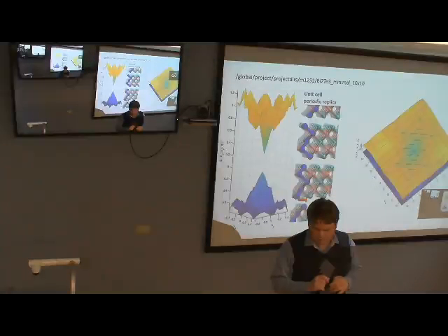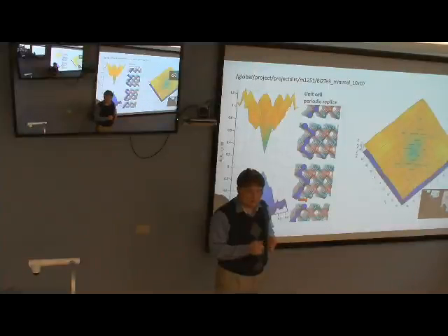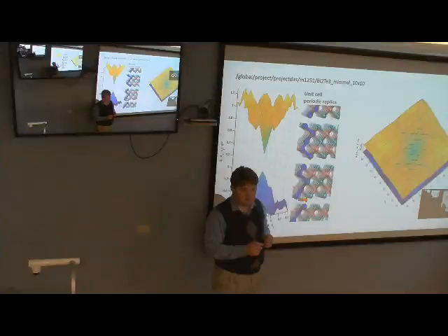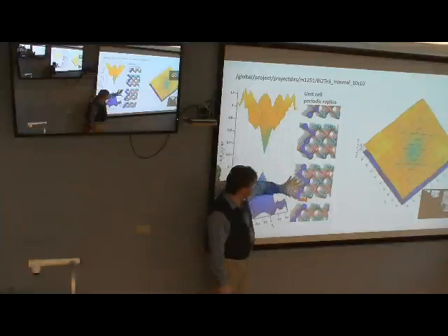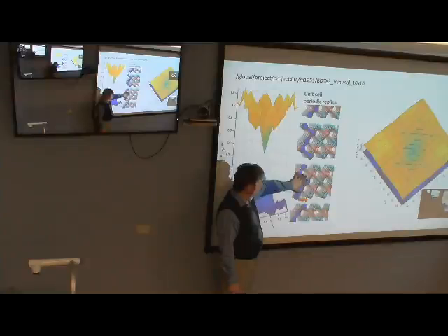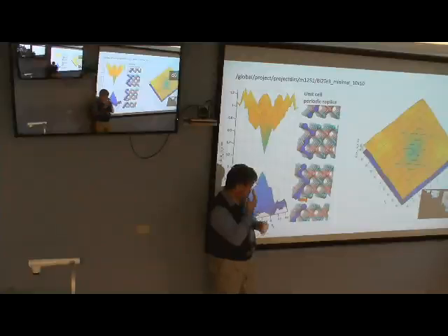So one of these materials is bismuth telluride. Bismuth is trivalent, tellurium is divalent, so the stoichiometry is bismuth 2, telluride 3, and it is similar to Dr. Colbert's question to David yesterday. It is a 3-dimensional material in terms of synthesis, so it's bulk, periodic in all 3 directions. But the internal structure is composed of layers that do not have chemical bonds between them, same as in graphite compared to graphene.